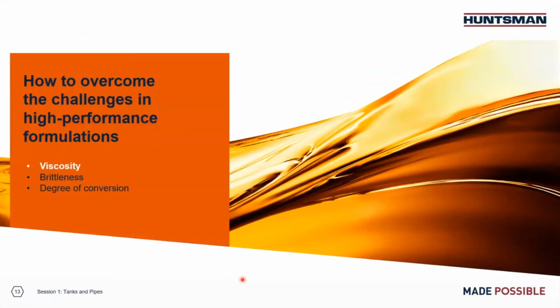So thank you very much, Yong. So in summary, the aromatic content leads to hydrophobicity and good thermomechanical properties. As you've shown, the hydroxyl group supports adhesion formation, and the ether group within the epoxy cannot be hydrolyzed, which is good for chemical resistance. So in addition to that, as you just explained, high functionality leads to high cross-linking density and as a consequence delivers durability. But increased functionality can also lead to high viscosity of the formulation.